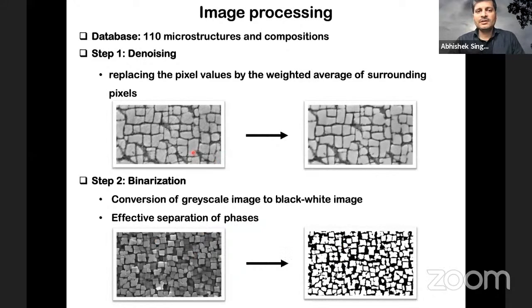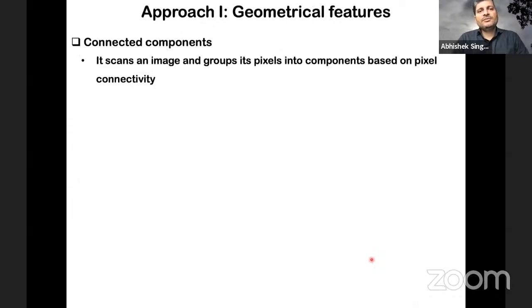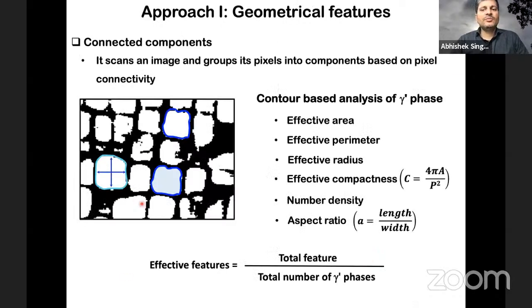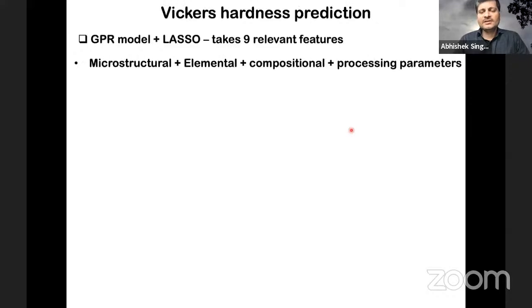So this is for us nickel-based superalloys. Here you have well-defined gamma and gamma prime phases, and after binarization, every pixel will have either a 0 or 1 value. So we have to put in a threshold to do this job. Then we use connected components to get these geometries. Once we have the white areas in certain geometrical arrangements, and black areas in certain geometrical arrangements, we go on and calculate the effective area, effective perimeters, effective radius, etc.